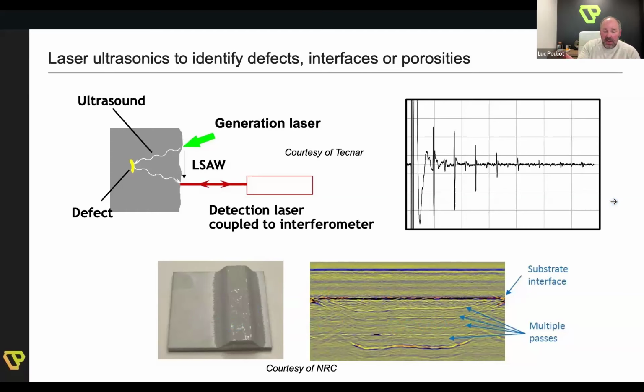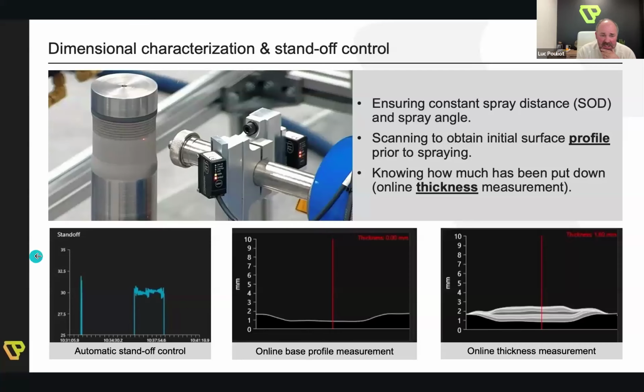If you use that kind of technique on a cold spray sample like that, you can even resolve those miniature interfaces that correspond to the multiple layers, or multiple passes, that you're depositing over time by going back and forth with the gun in front of the test plate. Those interfaces, you can see them as defects, if you will, or disruptions that the sound wave will be sensitive to. To conclude on that technique, it can even do much better in terms of resolution. Theoretically, it can sense a difference on the order of one interatomic distance, but that would be overkill anyway for cold spray. So we're integrating that as we speak in the Smart CSAM platform.